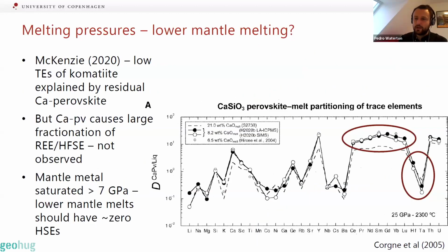There is an alternative proposal for how you get these low trace element contents, and that is that the melting happens in the lower mantle with residual calcium perovskite. This idea comes from McKenzie 2020, and he argued that the low trace element contents of komatiite could be explained by residual calcium perovskite. But the problem we have with this is that calcium perovskite causes a large fractionation of the rare earth elements, which are pretty compatible in calcium perovskite, from the high field strength elements. This is a bit offset by the opposite relation in magnesium perovskite, bridgmanite, but you would basically need all komatiites to form with the exact ratio that this just cancelled out, and it seems kind of unlikely.